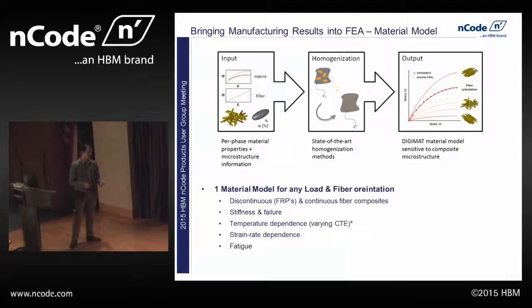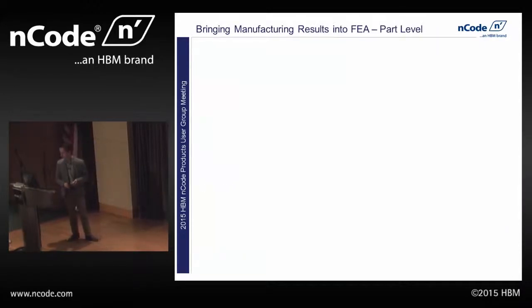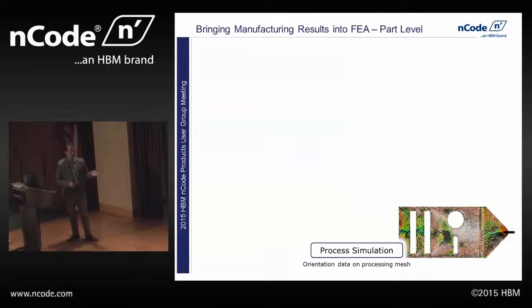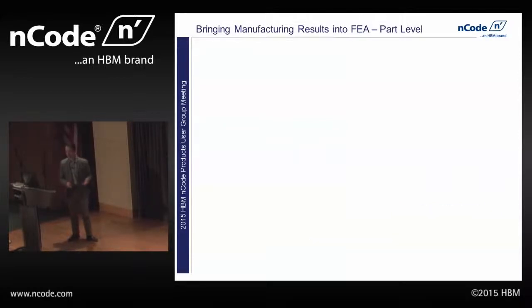So stiffness, failure, we can handle temperature dependence, because obviously these plastics are very temperature dependent, as they alluded to earlier, but the glass fibers are not so temperature dependent. We can look at strain rate dependence because you have the same kind of thing happening there between the plastic and the glass fibers, and we can look at fatigue. So we talked about it at the base material level, but then how does that interaction happen at the part level?